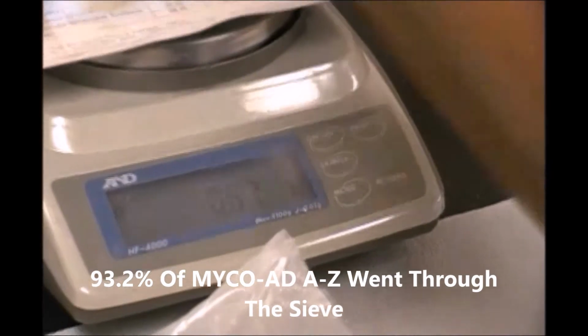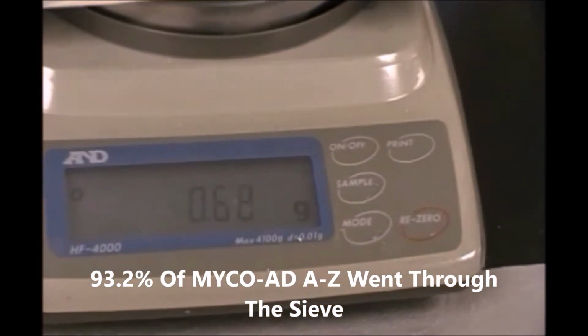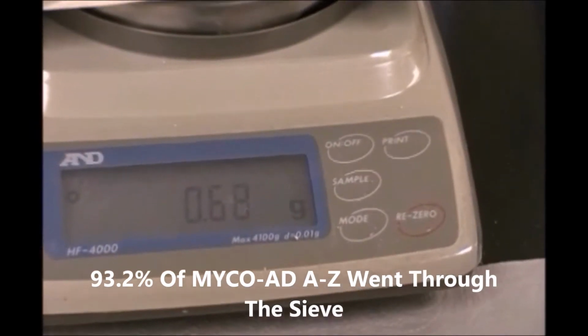The product will then be weighed again. You will see that out of the 10 grams of product, only 0.68 grams remain, meaning that 93.2% of the product went through the sieve.